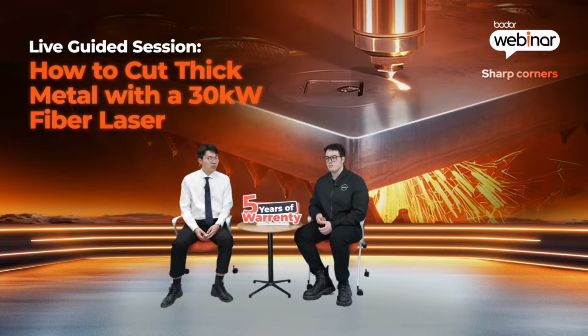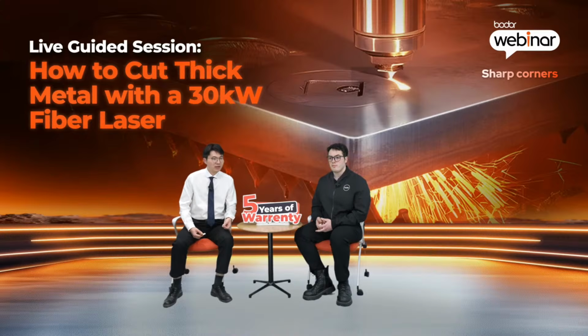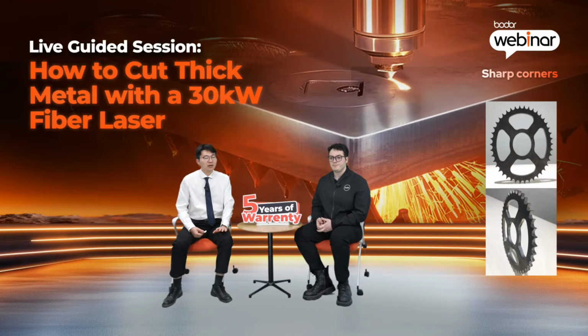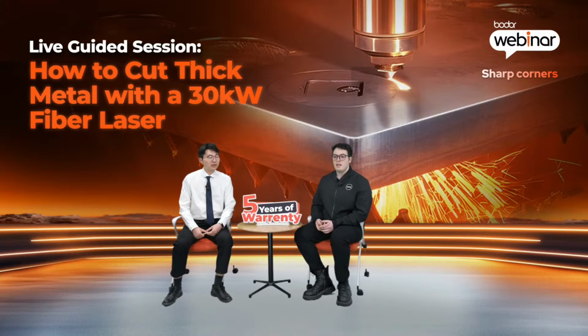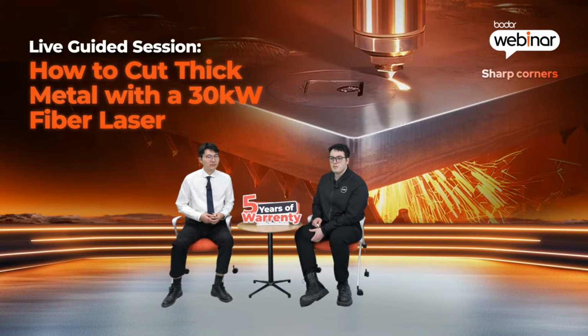And let's give you another sample. Sharp corners. Laser cutting can produce sharp edges without overburn, but plasma cannot achieve sharp corners. So for parts like gears, this makes a big difference. Let's look at this example. This is a 500 millimeter gear, 12 millimeter thick carbon steel, with 42 sharp teeth and a corner radius of just 1 millimeter. Laser can achieve this directly with clean and precise edges.